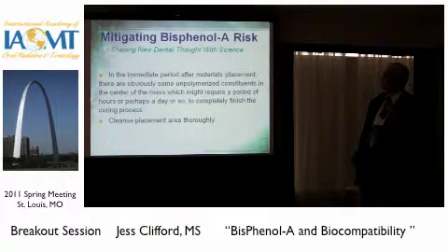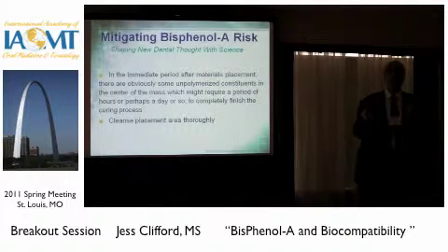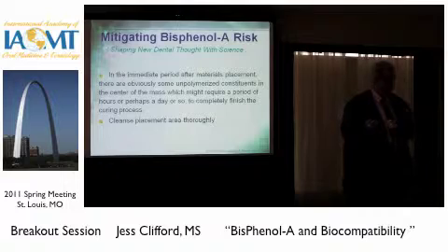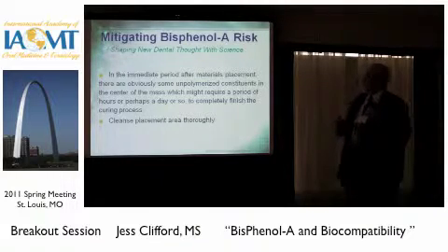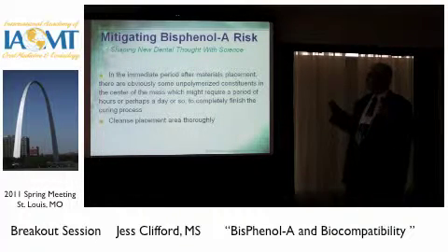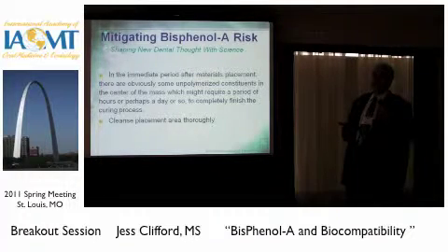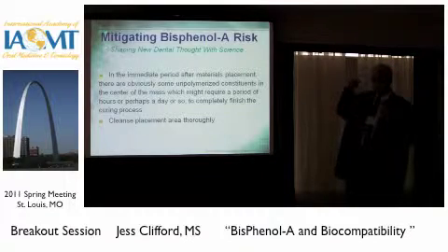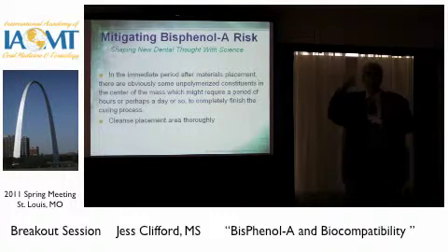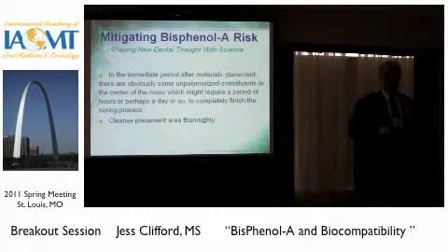In the immediate period after materials placement, there are obviously some unpolymerized constituents in the center of the mass that you have placed. They may require a period of hours or perhaps a day to completely finish the curing process, but usually if we get at least 1 millimeter depth of cured material, raw bisphenol A and other constituents of concern do not migrate through the cured layer.